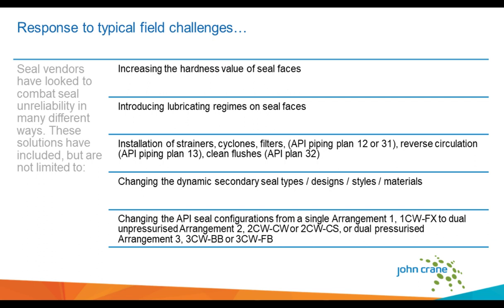Removing the traditional dynamic secondary seal with what is termed a non-pusher style seal, such as a rubber bellows or a metal bellows design. This removes the dynamic movement directly in relation to the shaft or the sleeve and will reduce potential for fretting. And finally, changing the seal arrangement and API lubrication from an API seal arrangement 1 to use dual seals and self-contained seal support systems, either as a pressurized arrangement 3 or an unpressurized arrangement 2, to ensure that the clean lubricating liquid in a controlled environment is at all times being circulated around both the secondary and primary seal to ensure optimum seal chamber conditions.